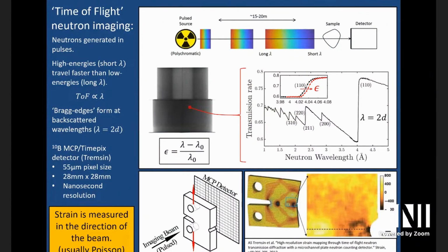But the point is, the best we can do in terms of this geometry is backwards. That happens from a crystal that's got lattice planes already perpendicular to our incoming radiation. These lattice planes will scatter directly backwards, so the scattered radiation is going back towards the source. We can't do any better than that. Once you've gone backwards, there's no other geometry that will be allowed. So this wavelength is the last point in the graph where we can scatter radiation for that set of lattice planes. And so we have a jump. We pick a point in that wavelength, and nothing past that wavelength can get scattered by that set of lattice planes.